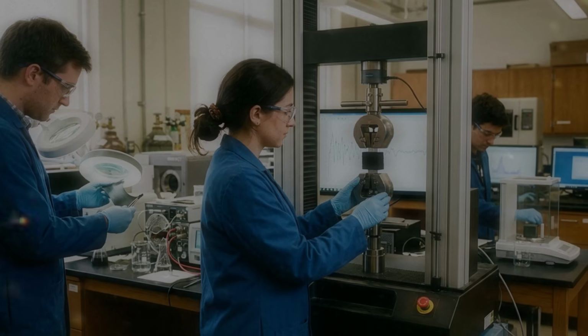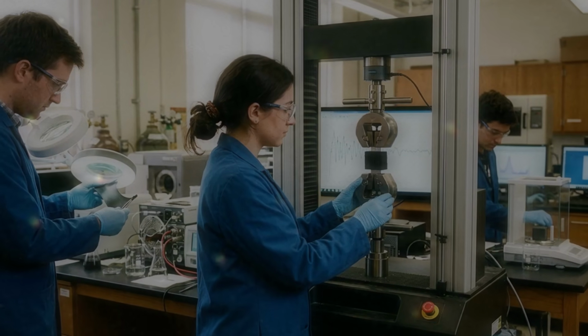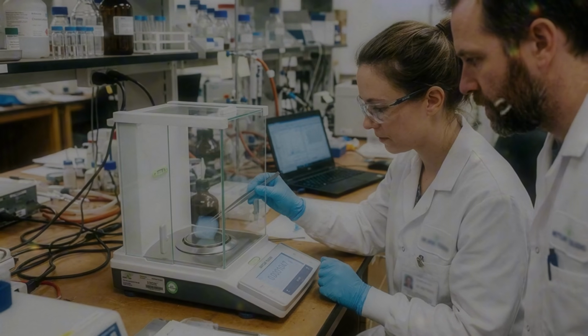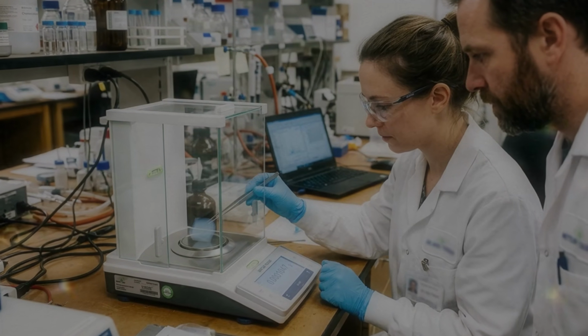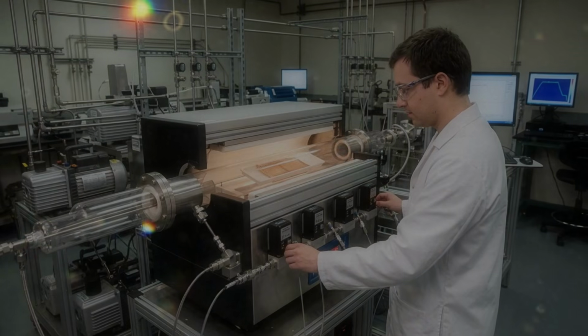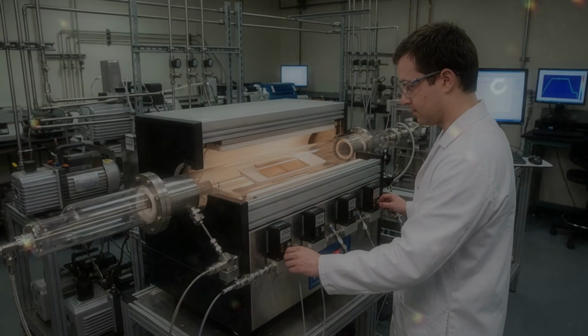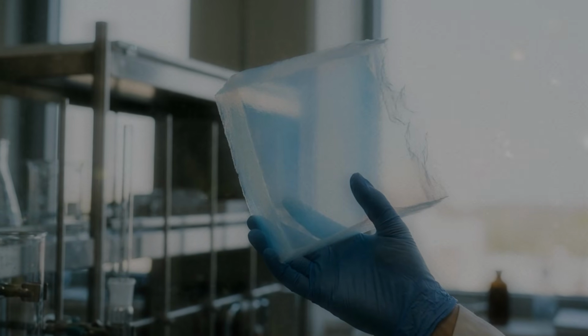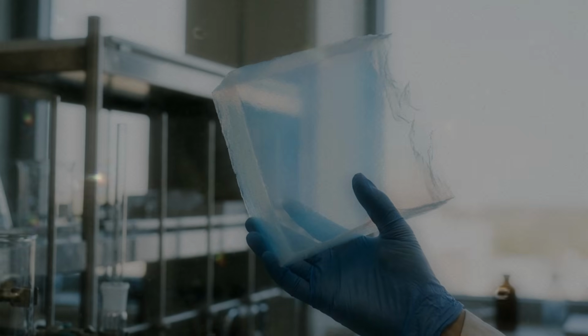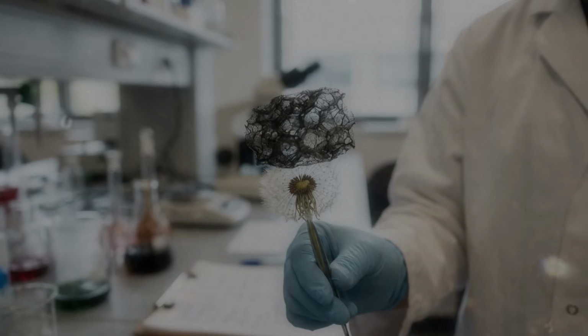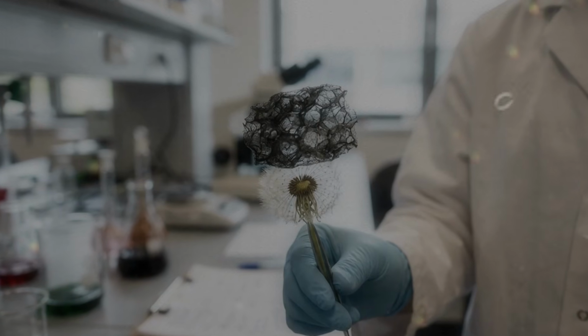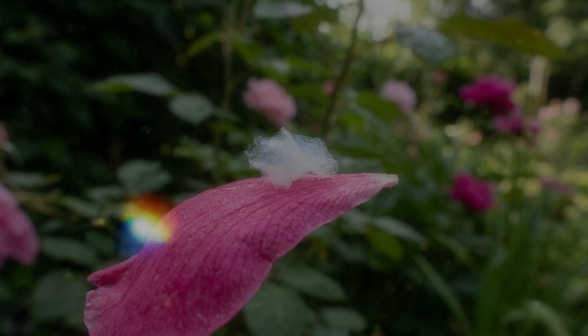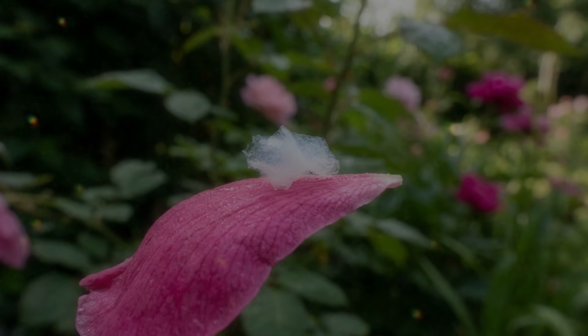Density changes across the sample can be equally troublesome. If one region contains more solid material, it may be stronger and more conductive. A lighter region may deform first. In an electrode, this produces uneven current. In insulation, it creates paths where heat moves more easily. Uniformity becomes harder as the object grows. A small sample can be carefully controlled. A large panel contains greater distances, larger temperature differences, and more opportunities for bubbles or contamination. Industrial manufacturing must produce the same architecture repeatedly, not merely once.